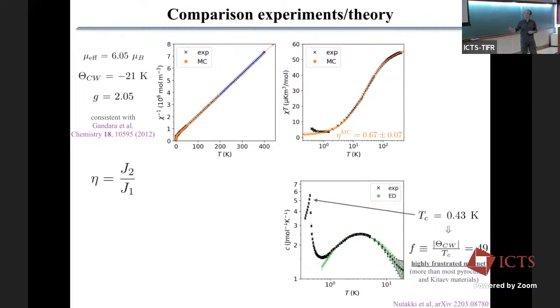But yes. And so we compare the Monte Carlo simulations with the experiments, and we can fit the experiments from like 300 Kelvin down to roughly 1 Kelvin or below. So what we see here are 2 things. One is that the ratio of J2 over J1 to fit this data is of the order of 2/3. So there is only a ratio of 2/3 between the first and second nearest neighbor in this material. And the second one is our simulations do not show the long-range order at low temperature.